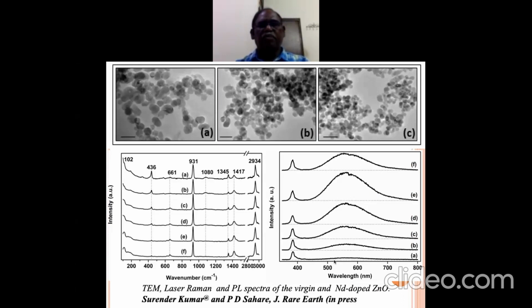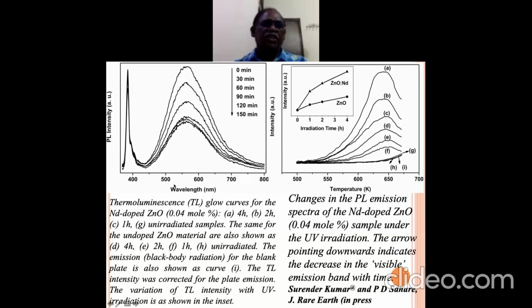And from the application point of view, you can see that if we expose this nanomaterial to UV light, the surface defects might be getting more created over there, or they change, and therefore this green emission changes with the exposure time. So if you keep the power of your UV the same and go on changing the exposure time, you will see that there is a change in this green band, and by this you can also monitor your UV radiation.